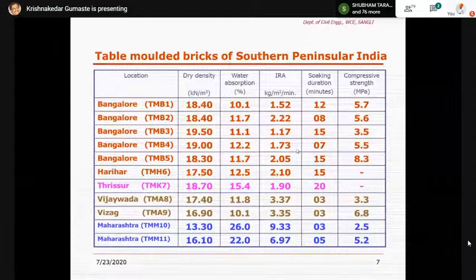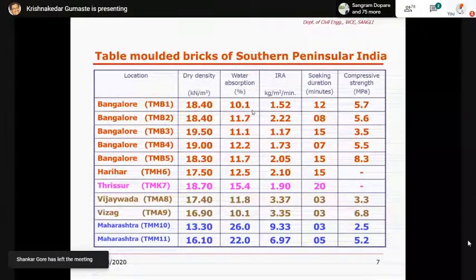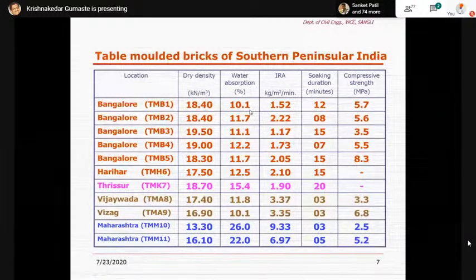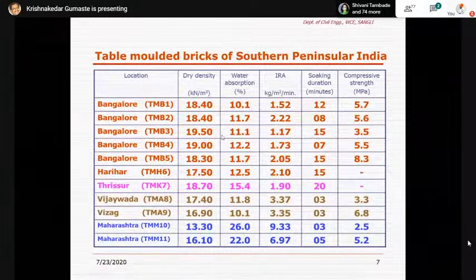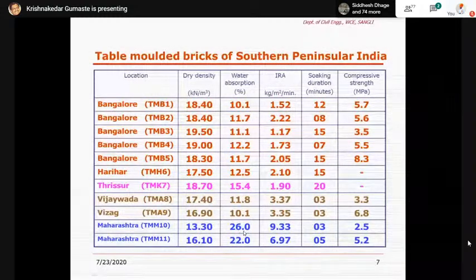The other common characteristic we see is water absorption. The code says that up to class 12 and a half, the permissible water absorption is about 20%. And as per IS 1077, bricks above class 12 and a half, that is, bricks having 12 and a half megapascals and above, should have a water absorption of less than 15%. As you can see, the majority of the bricks show lower absorption than 20%, but bricks of Maharashtra show a very high water absorption of 22% and 26%. Irrespective of that, we have been largely using bricks in spite of very low compressive strength and high water absorption, which nonetheless doesn't satisfy any codal provisions.